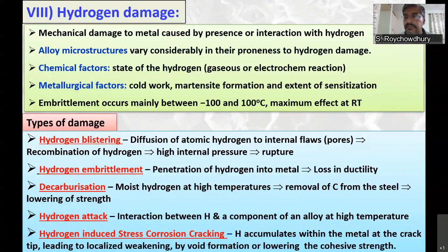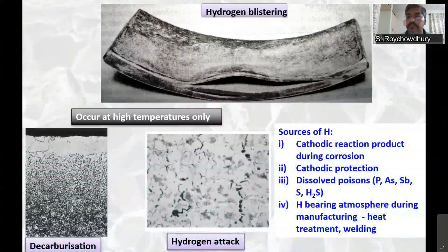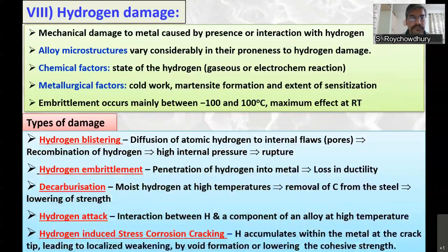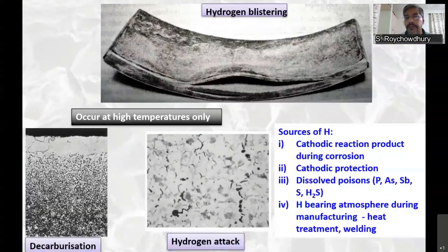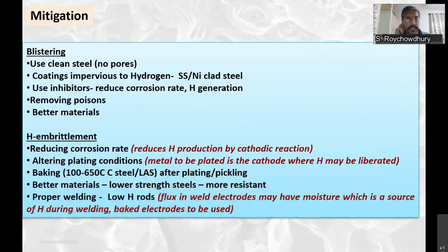Hydrogen attack inside the metal, also at high temperatures, can react with carbon and form such bubbles. So these bubbles of methane can form inside. This is CH4, carbon reacting with hydrogen to form methane. And again, the problem is due to internal pressurization. Another problem is stress corrosion cracking. As I told you, hydrogen-related SCC is one mechanism. If that mechanism is operative, presence of hydrogen will aggravate the situation.